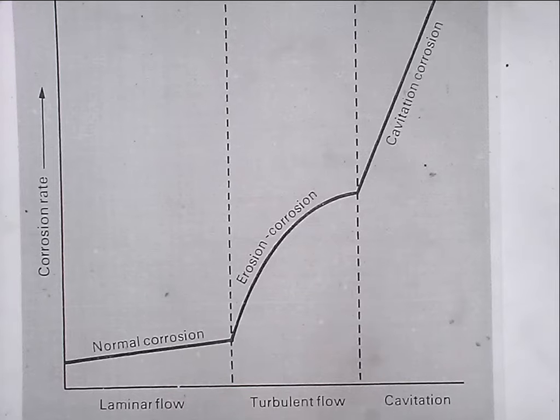So what's happening here is, under laminar flow conditions, you're just getting the chemical corrosion, the electrochemical attack. As the velocity goes up, you're now introducing a mechanical component to the attack, to the damage. So you're getting a combination of corrosion and a turbulent flow erosion, which we're going to talk about in a minute. If the velocity gets very fast, then the failure is mechanically dominated. So at low velocities it's corrosion dominated, at high velocities it's mechanically dominated, and then you've got a spectrum of conditions in between.